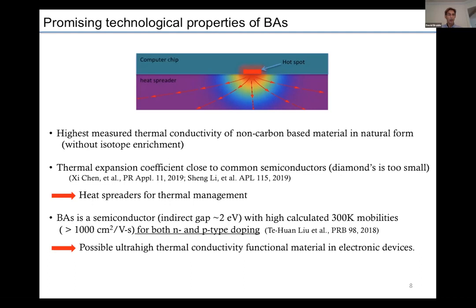Another interesting feature of boron arsenide is that it's a semiconductor, unlike diamond, which is an electrical insulator. And it has high predicted mobilities for both N-type and P-type doping, which is quite unusual. And so that suggests it's possible to use as a functional material in electronic devices where its thermal conductivity is 8 times higher than that of silicon.